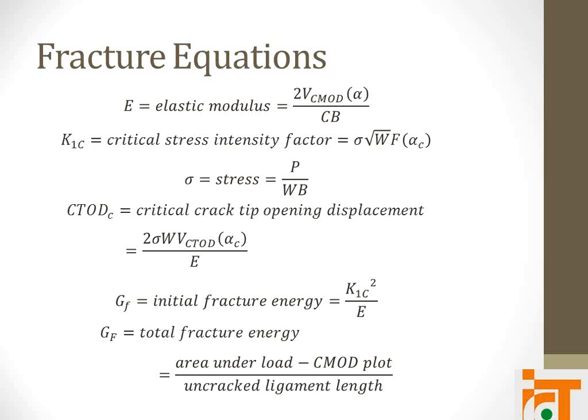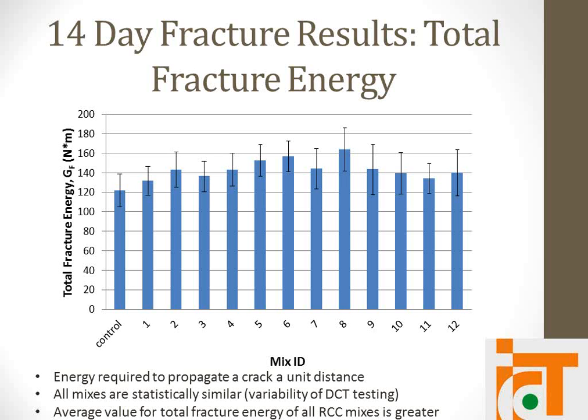Just for reference, here are some of the equations used to calculate fracture properties. The main ones that I'll be talking about are the K1C, which is a material's resistance to fracture or crack propagation, as well as the total fracture energy, which is the energy required to propagate that crack. So these are the fracture results in terms of total fracture energy. This is typical variability for DCT testing, and we can't statistically conclude that RCC is better than a typical mix, but all the average values are greater, and we can have some confidence in making that decision.